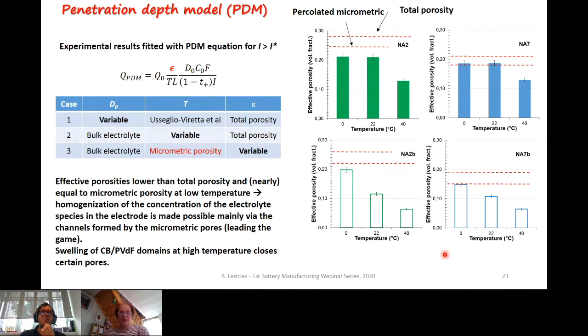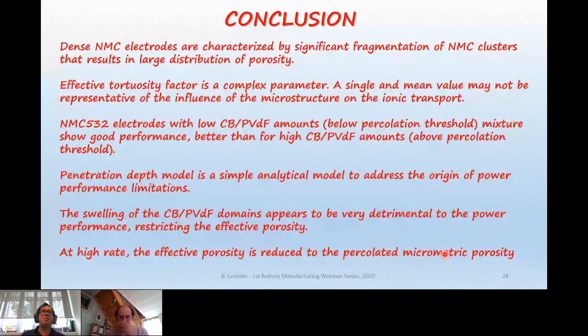We are not 100% sure, but I think this is an interesting way to look at the behavior of these electrodes. So I'm at the end. To conclude, we've seen that these dense NMC electrodes are characterized by a significant fragmentation of NMC clusters that results in a large distribution of porosity. The effective tortuosity factor is a complex parameter. This is absolutely not new, but we confirm it. And a single mean value may not be representative of the influence of the microstructure on the ionic